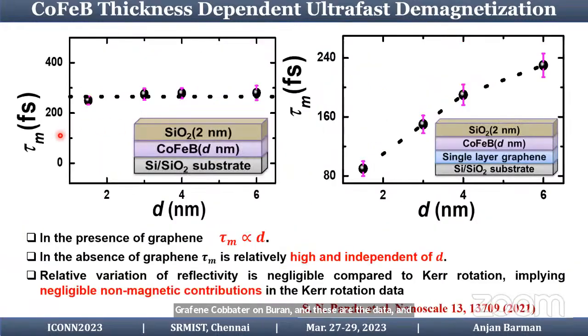And here is the plot, which shows that for pure cobalt iron boron, the demagnetization time is high and it does not vary with d, whereas for graphene cobalt iron boron, there is a stark change. So it actually increases from 80 to 240, that is a factor of 3. So what is the reason behind it?